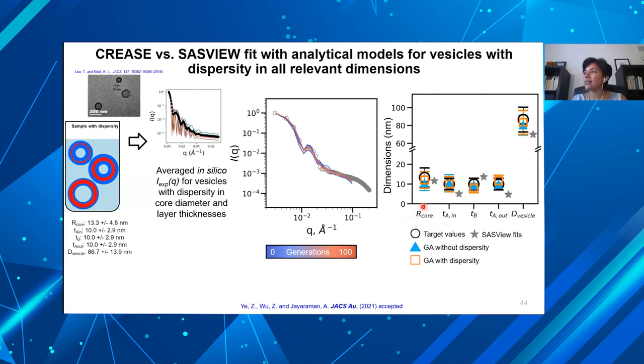And you can see this is the core diameter, the inner layer thickness, blue layer and red layer thickness, that's TB, next layer thickness, that's TA out, and then the sum of all of that. So now you can see that the target values from our original experiment is in black and our genetic algorithm in dispersed and without dispersities in the color. We can handle dispersity really well in genetic algorithm. It also tells us how much dispersity we have. You can see it gets pretty good agreement.